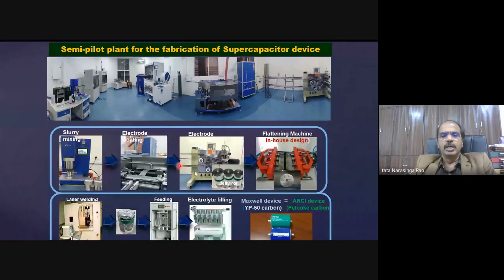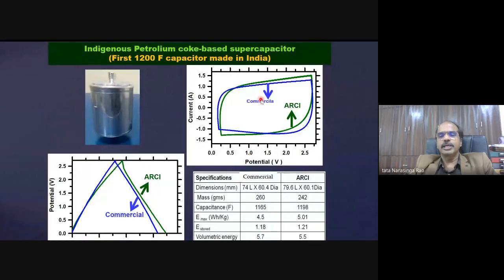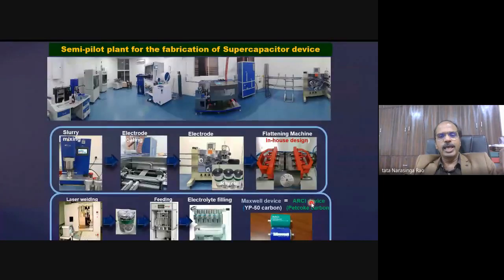You can see here the cathode and anode, the negative and positive electrodes, with a separator, the white one, running, and then rolling it in the form of huge jelly rolls. Finally you flatten both sides, put it in a can, and make a cell. And now I have a Maxwell device made with YP50, the blue one, and the ARCI one, the green one. We are on par in size and capabilities. You can see ARCI and commercial are very close, both in charge-discharge and energy density, and that is because of the laser welding technology.